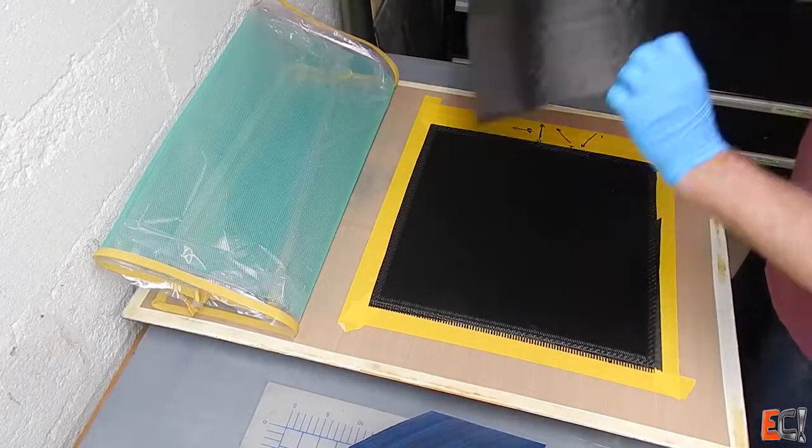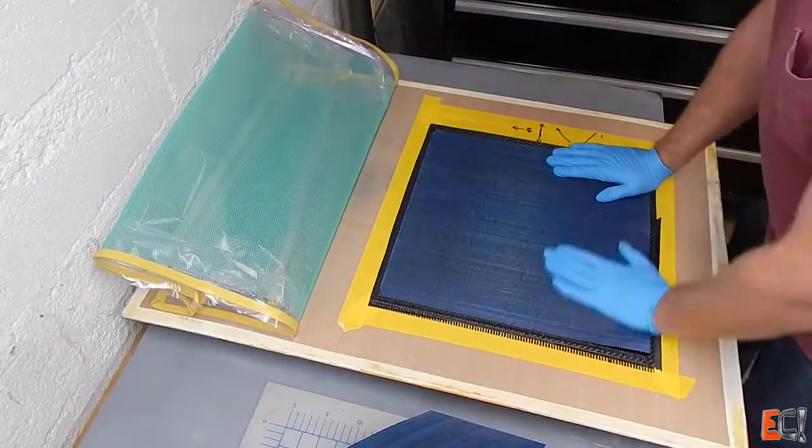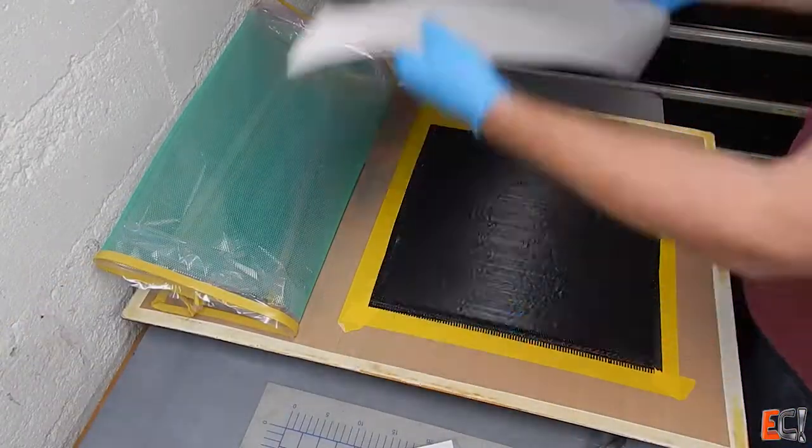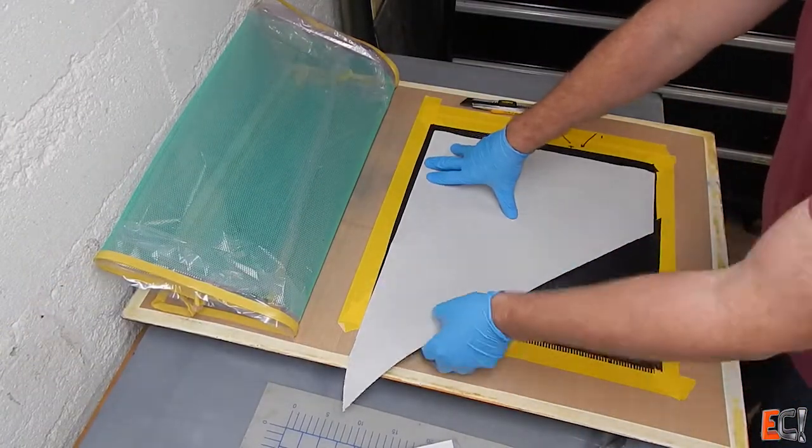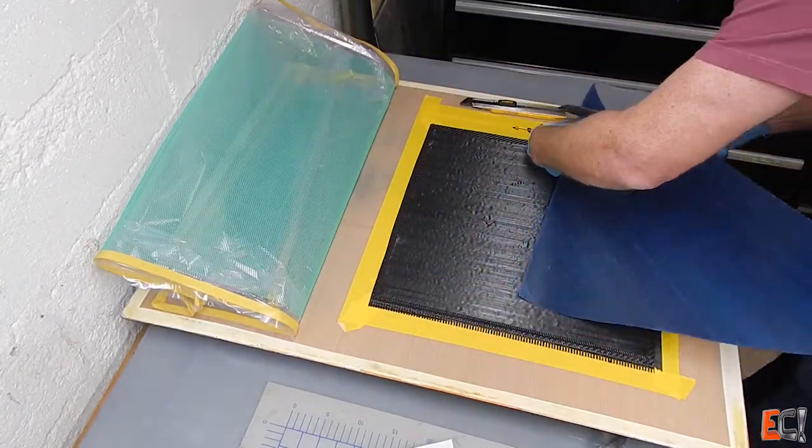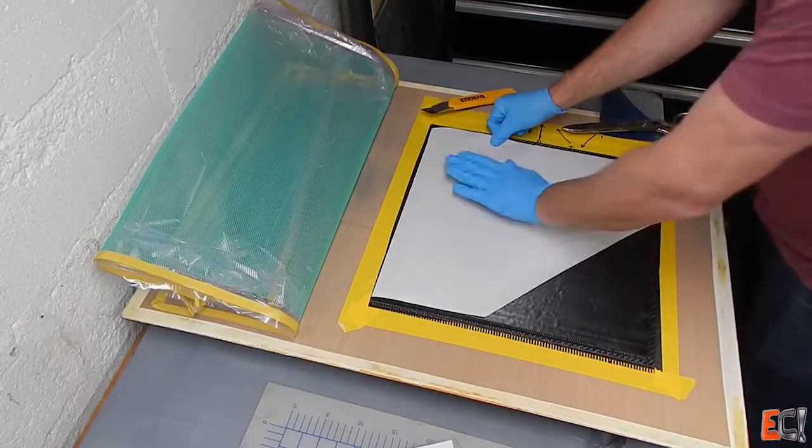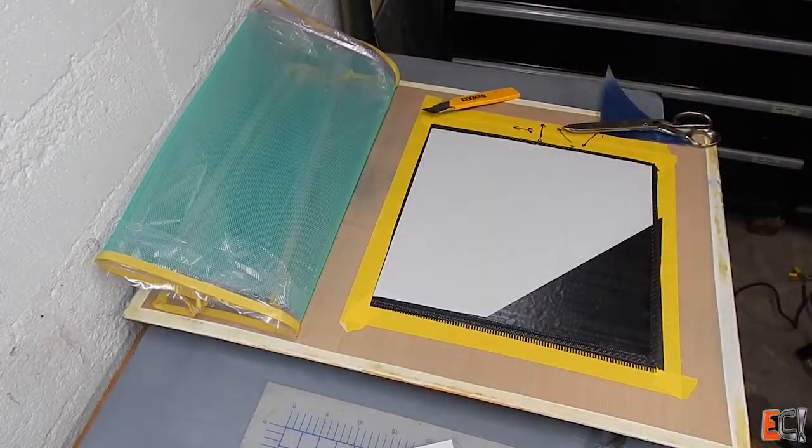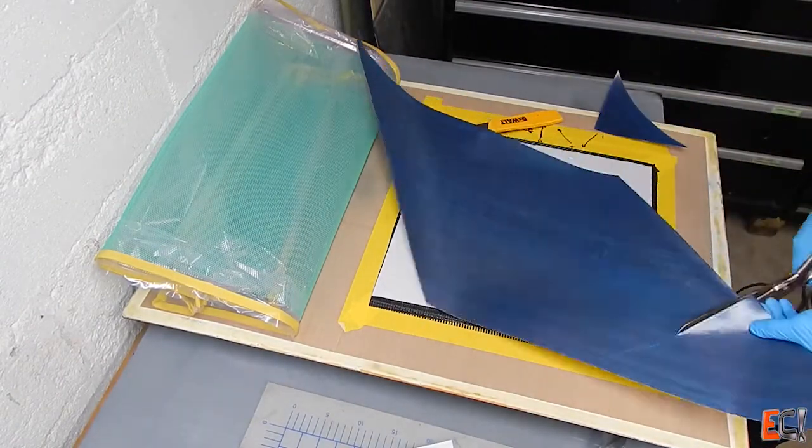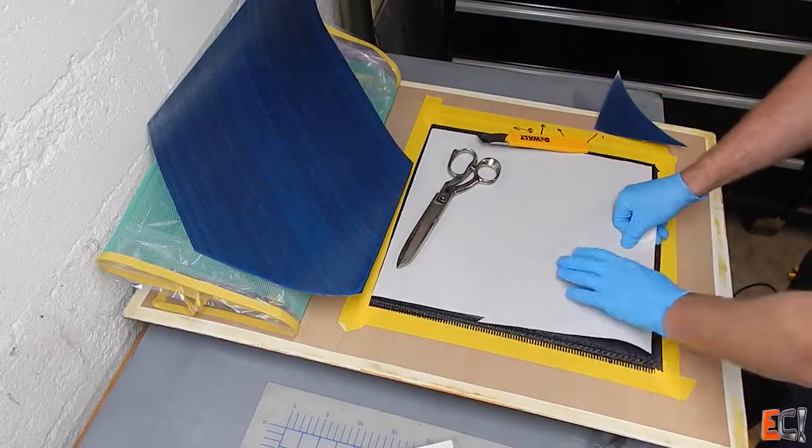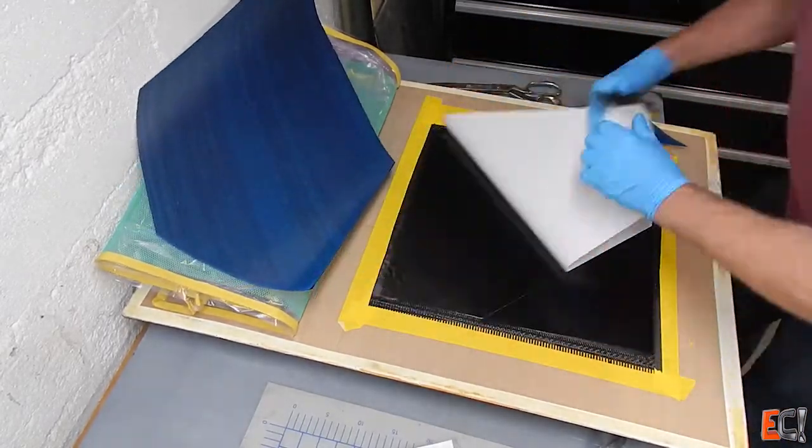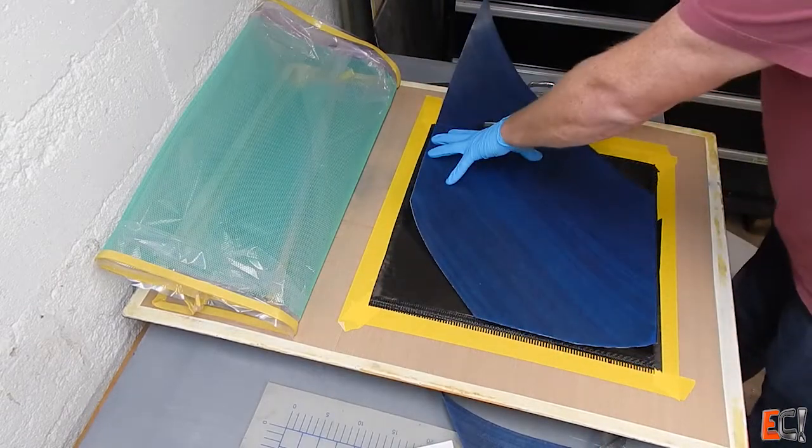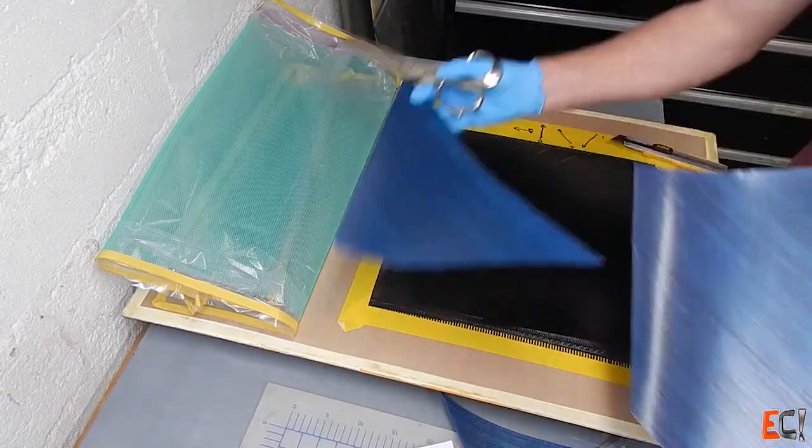Because it's the neutral axis it shouldn't make much difference but I should have been paying more attention. And now I'll go back and work in the opposite direction keeping all of my plies mirrored about that mid-plane laminate and this should make the final product nice and flat with less likelihood of warping.